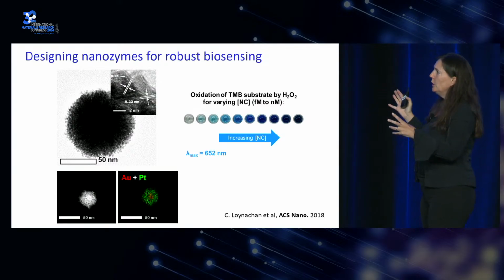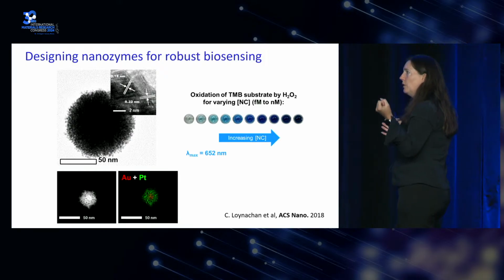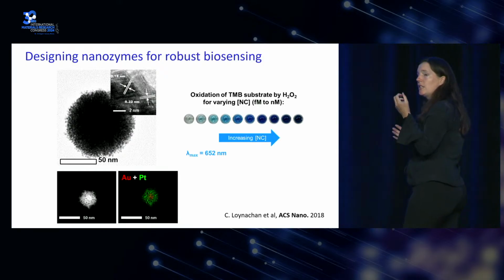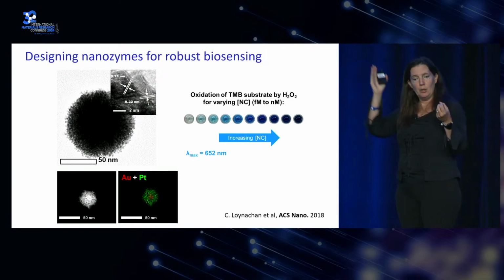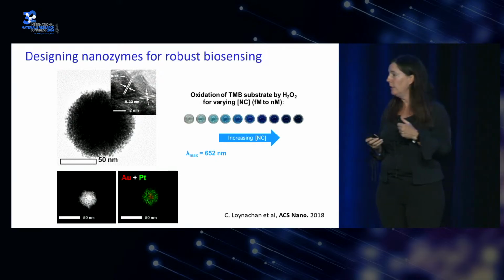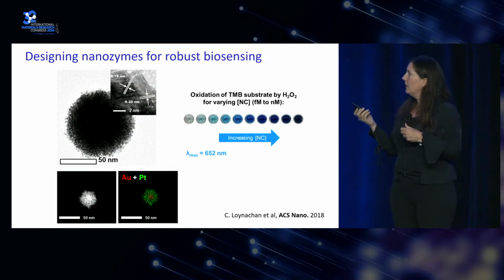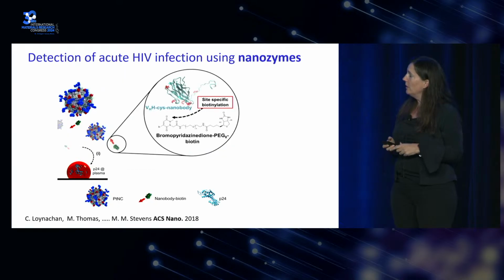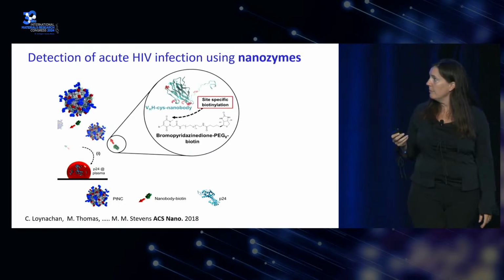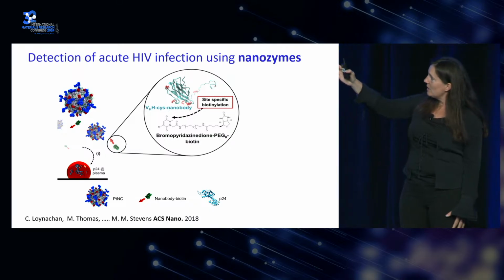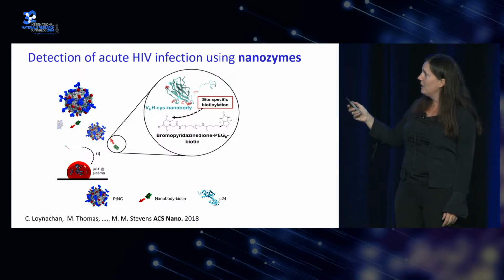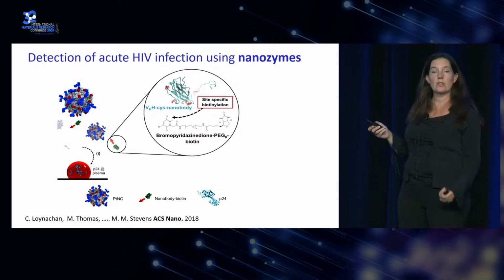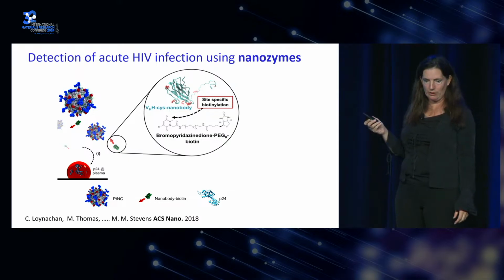And so you can use them the same as you would use a gold nanoparticle in a COVID test, for example, where you see that red line, but you're producing a much stronger color change. And that means you can detect much lower concentrations of your target. So we can take these particles, we decorate them with antibodies that can recognize this protein called P24, which is on the surface of the viral capsid for HIV.